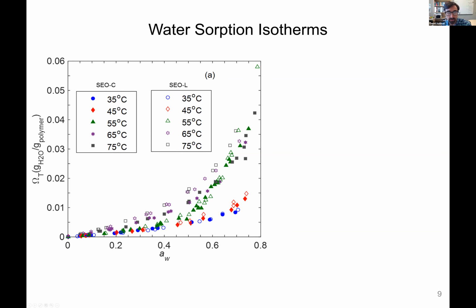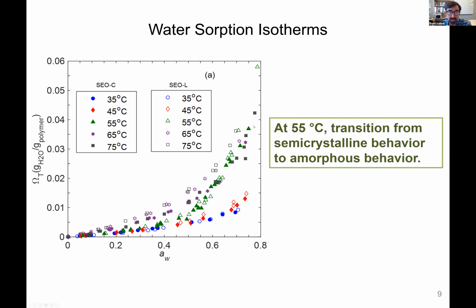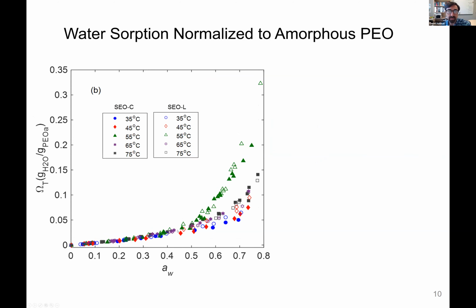And actually you can see at 55 degrees C, this transition from the semi-crystalline material to the amorphous material. What we can actually do is, if we normalize our water absorption to grams of the amorphous polymer rather than grams of total polymer, we can get a collapse here of all the isotherms at low activity.